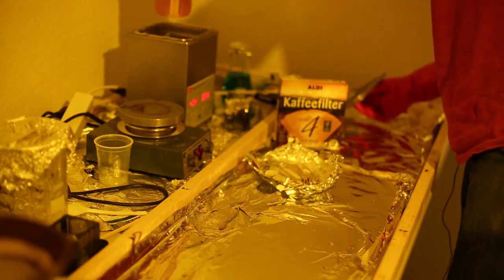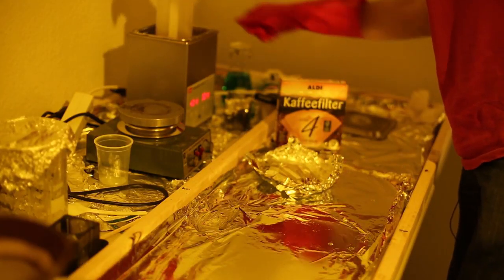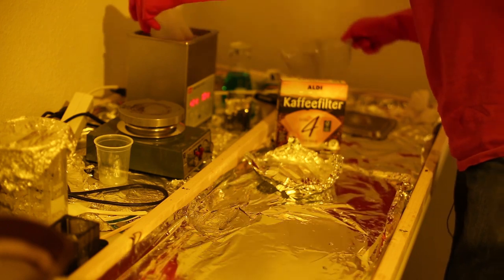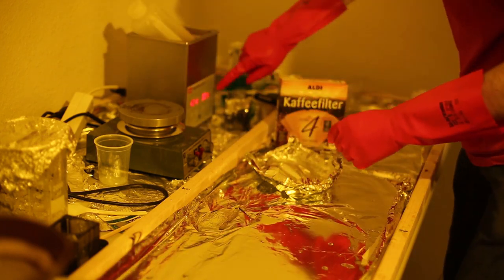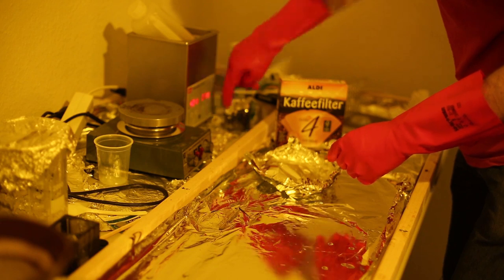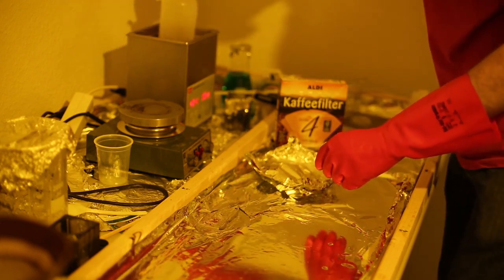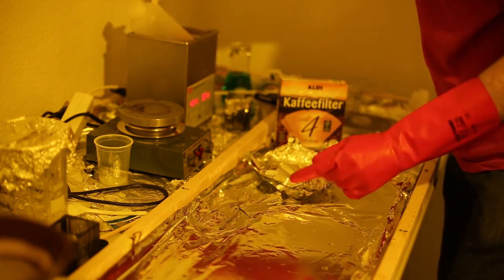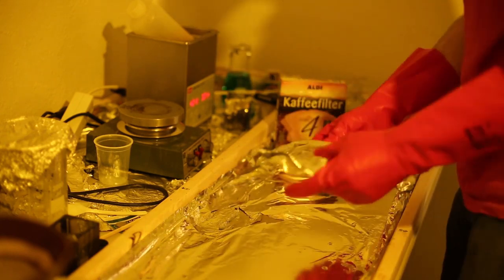In a final step, the filled coating bottle is placed into an ultrasonic bath for about 1 minute to get rid of even the tiniest bubbles, which make for a bad coating. When switching on the device, all the bubbles rise to the top. Now the gelatin is ready for coating.